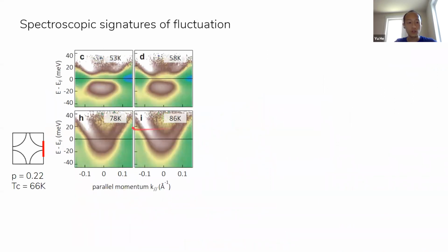Now we can use photoemission to examine the momentum structure of that spectra. So what is shown here is a very high statistics, high resolution scan just along the Brillouin zone boundary. And we can divide out the Fermi function because we have such good statistics to recover some of these upper branch of the Bogoliubov quasi-particle dispersion. The top two panels are below the bulk Tc, and the bottom two panels are above bulk Tc. And I hope you agree with me that there is still a substantial band structure anomaly or disruption at the Fermi energy, even at 13 Kelvin above Tc.